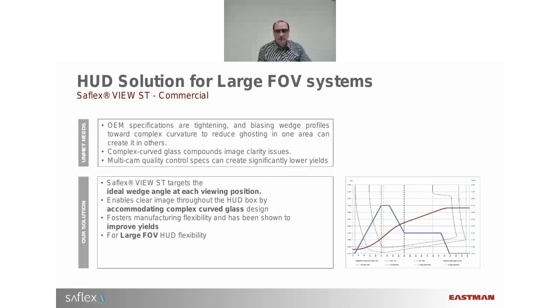In the right bottom, you see an example where the red line is the thickness profile. If you go from the left to the right, you see first the bottom of the windshield, and on the right the top of the windshield, and you see the thickness is growing. And related to this, the wedge angle marked in blue is changing over the head-up display zone. So this enables to have a good viewing for all drivers, but it also enables to have a larger field of view.